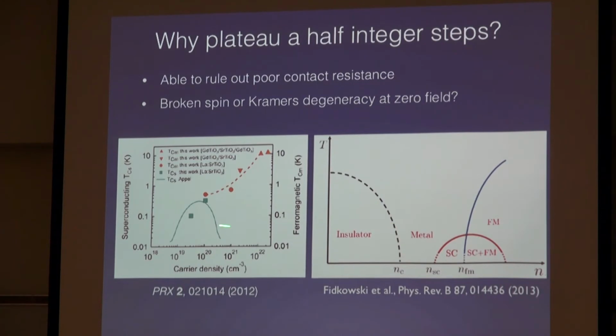Something else that's perhaps more interesting goes back to thinking about what ground states you have in strontium titanate. We've actually done work on this, and other people have too, not just us. If you look at the density behavior of the low temperature ground state of strontium titanate, one of the things that's been known for a very long time is that there's a superconducting dome relating the TC to the density. In addition to that, us and other people have seen above that superconducting dome ferromagnetic-like behavior. And for a range of densities, it turns out that both superconducting and ferromagnetic correlations exist. Which is kind of strange because they're seemingly opposite, at least from a conventional superconducting perspective. Superconductors pair like this, ferromagnetics pair like this. So we don't really know what's going on at this interface or at this coexistence place.